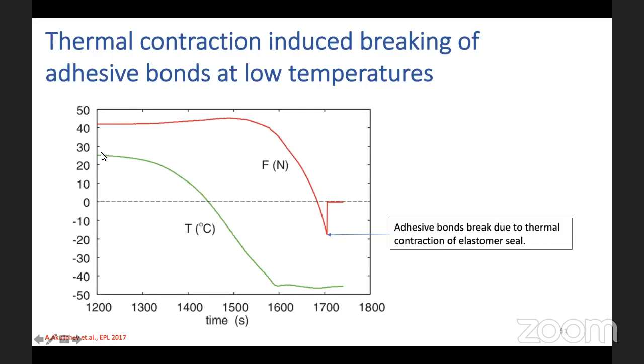as the temperature goes from ambient to minus 45 and then stays constant, the force that is holding the two surfaces together goes to a minimum, and then it breaks and the force becomes zero. This is what we call the adhesive bonds at the interface between the rubber and the counter surface steel breaking, and then it will lead to a catastrophic leakage. So in the Challenger disaster, this is what happened.